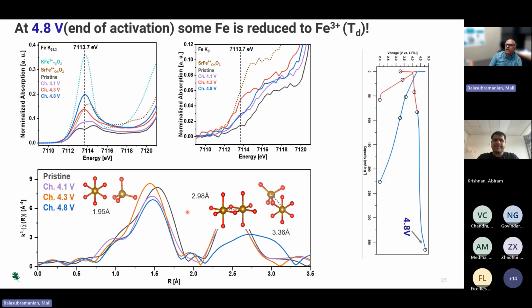This can be further verified by analyzing the EXAFS, where we believe that the average bond distance is consistent with iron being both as iron 3 plus in a tetrahedral site and iron 4 plus in an octahedral site. And additionally, you see that in addition to the edge-shared octahedra, a new intensity in the Fourier transform shows up, which is consistent with an octahedral-tetrahedral interaction, clearly showing that some of the iron is now in a tetrahedral site. So by using this combination of spin selective XANES and X-ray absorption spectroscopy, we can get a holistic view of the electrochemistry of the system.